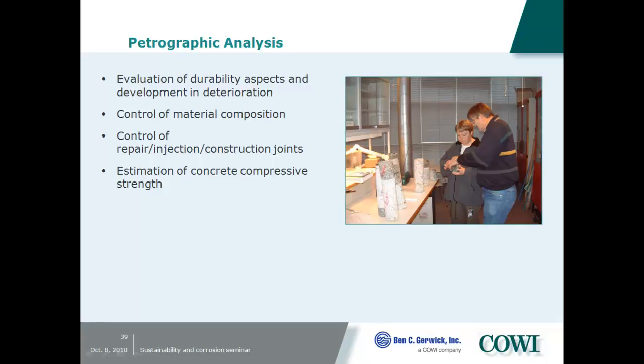Petrographic analysis, we use it to evaluate durability aspects and developments in deterioration, control of material composition, and I should say that this covers both macro and micro analysis when we say petrographic analysis. We can control repair and injection. We can also estimate the concrete compressive strength by looking at the porosity and the point count on the composition.